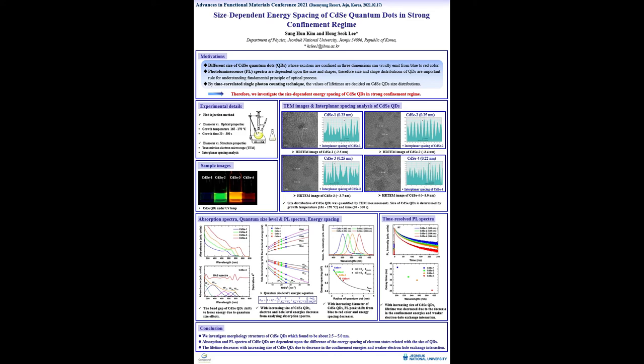The dependence of energy spacing on the measured diameter is shown in the graph below. This graph shows the estimated size of cadmium selenide quantum dots. The results using absorption peak agree well with the TEM observations of cadmium selenide quantum dots.